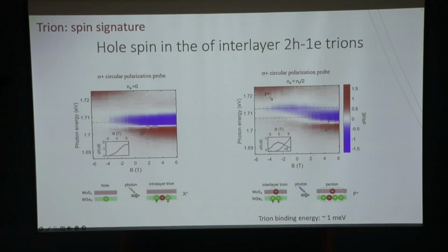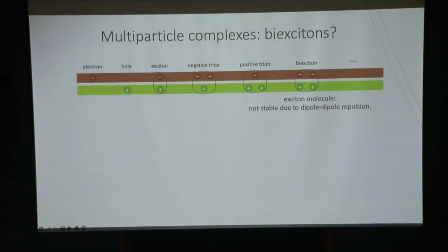So it remains more or less constant until the magnetic field is large enough. When the magnetic field is very large, this bound trion cannot benefit from it because it has a spin singlet. It does not have Zeeman splitting. But if you have a separated exciton and hole, then they are paramagnetic. They can lower their energy through Zeeman energy. Sooner or later, they have lower energy than the trion. Then you dissociate the trion, and that's when the trion disappears. Based on the Zeeman energy, we can estimate that the trion binding energy is relatively small, only at the 1 to 2 meV level. OK, so we check the box of the trion.